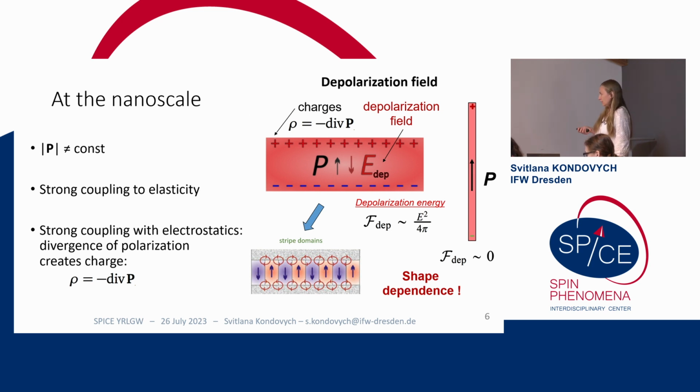The sample won't stay uniformly polarized, but will acquire a non-uniform structure in which the polarization field is a surface effect. Due to alternating charges on the surface, the polarization field is localized at the surface of the film, and with the additional cost of creating domain walls, it will result in a stable configuration. So at the nanoscale, ferroelectric texture exists, and it can be non-uniform and similar to a magnetic domain structure, for example.